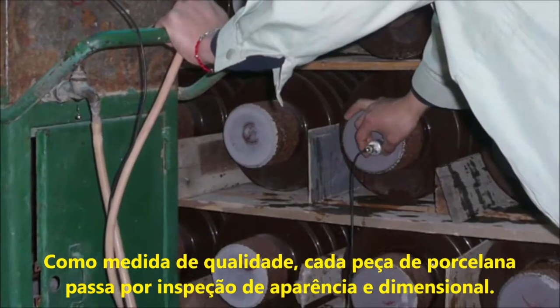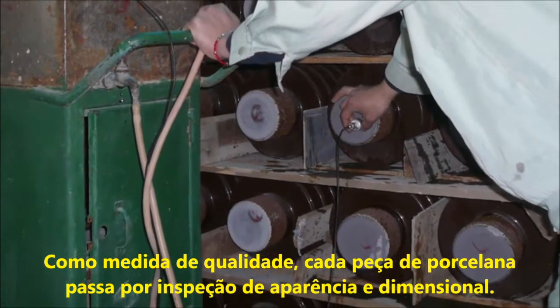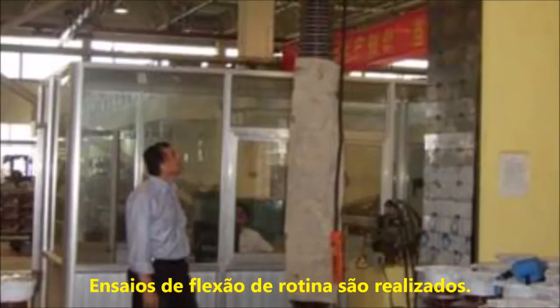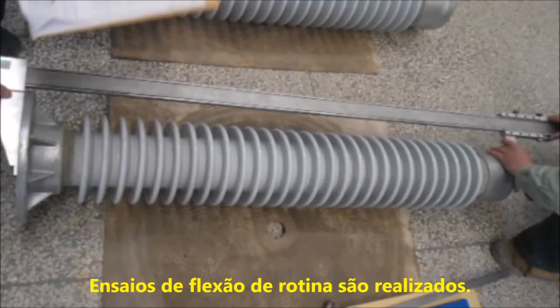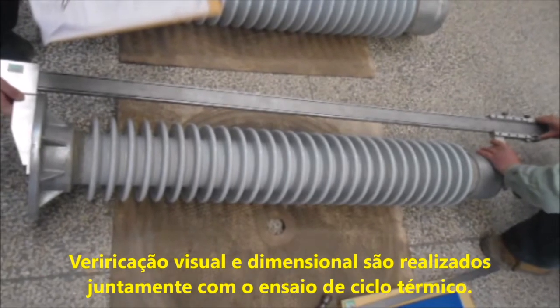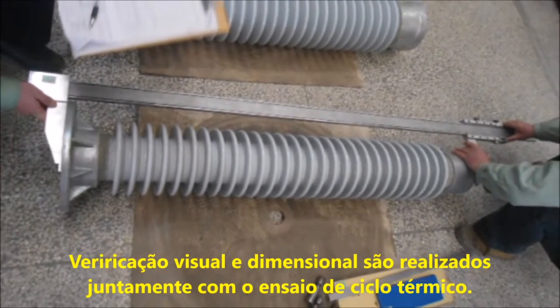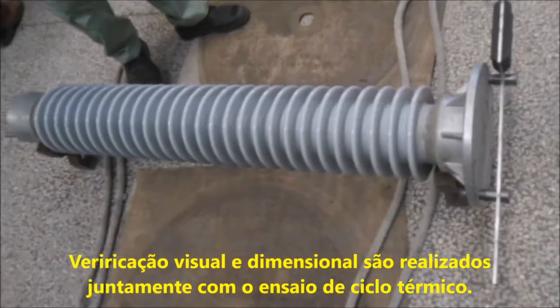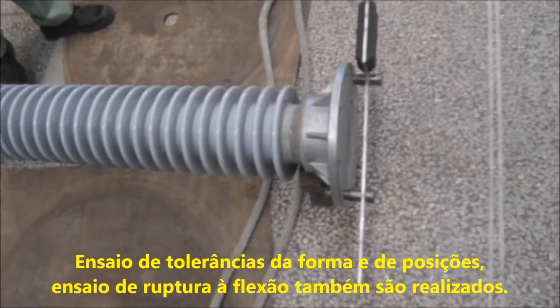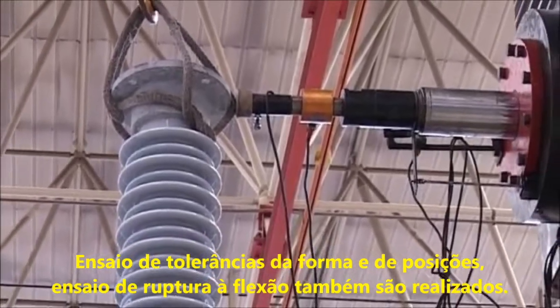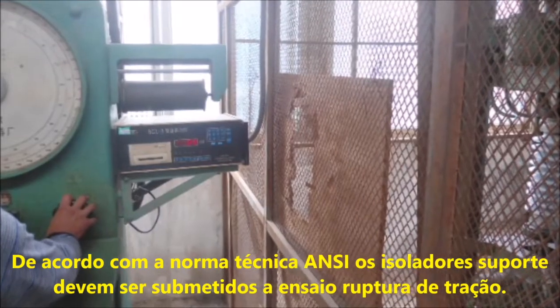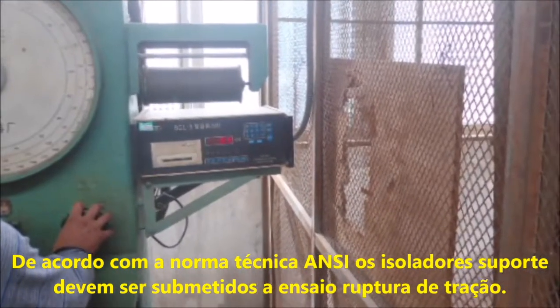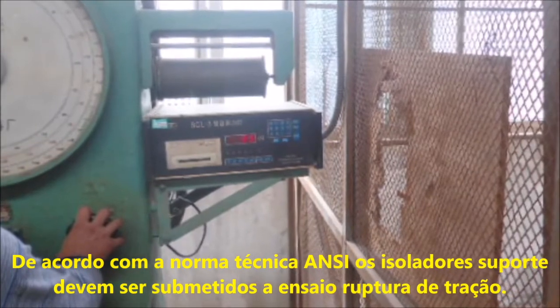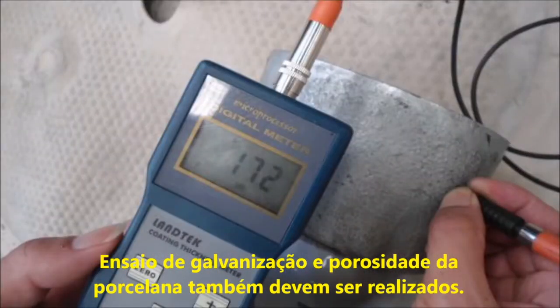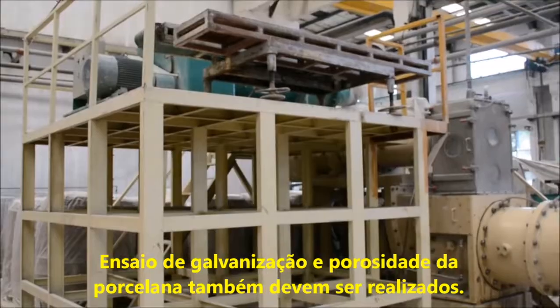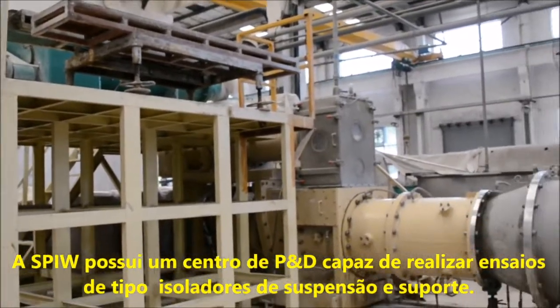Each piece of porcelain receives appearance and dimensional inspection. Routine bending load tests are conducted. Product spot checks for appearance and dimensional quality along with temperature cycling tests are conducted. Form and position tolerance test. Bending failure load test. According to the ANSI standard, station insulators undergo tensile failure load test, galvanizing test, and porcelain porosity tests. SPIW maintains an R&D center